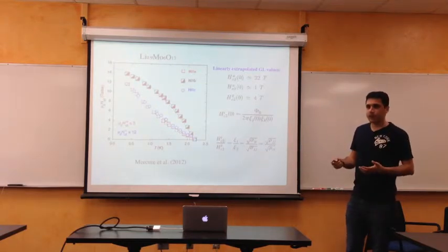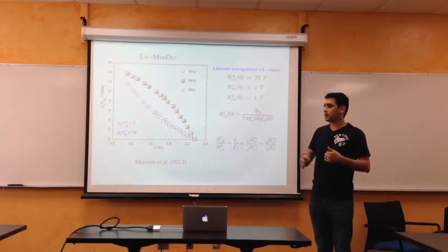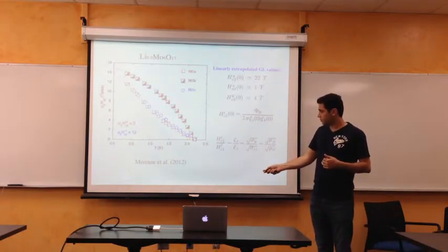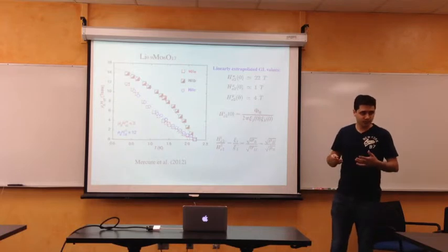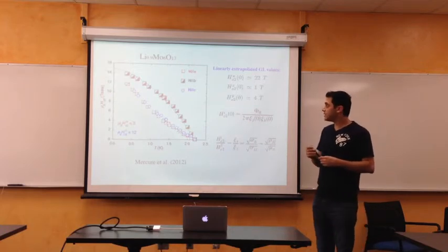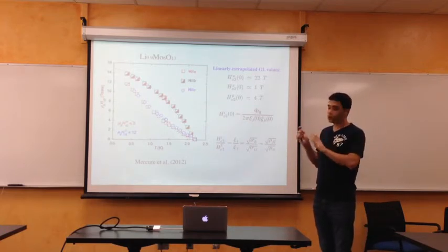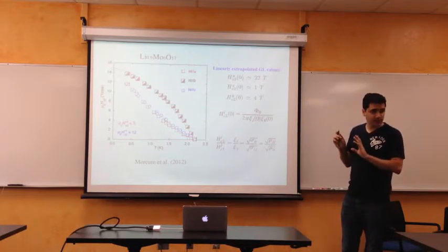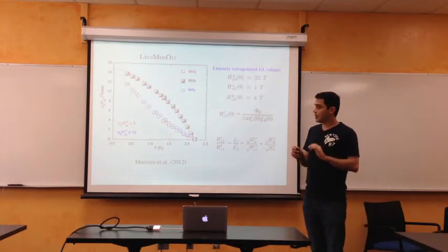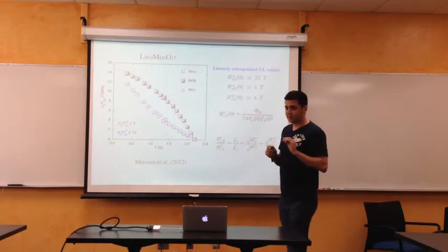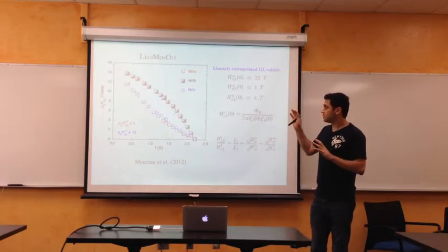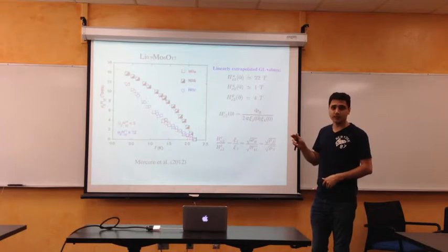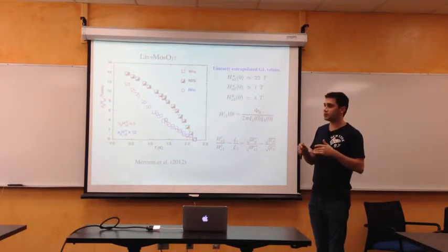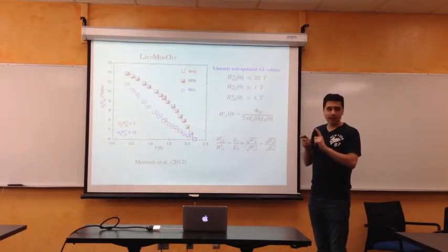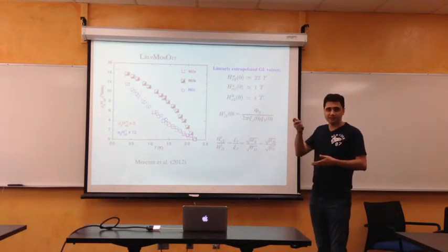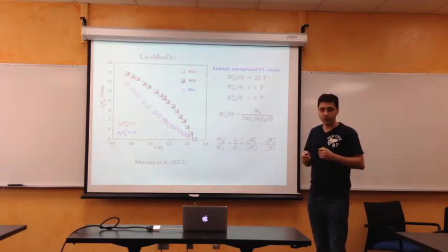So a proposal by the experimental group, and then our theoretical proposal, states that this is a strong candidate for a possible triplet type of pairing, right? But now I have to mention that there are several factors which can suppress this Zeeman splitting, in terms of preventing it from aligning, and make the field actually higher than HP.